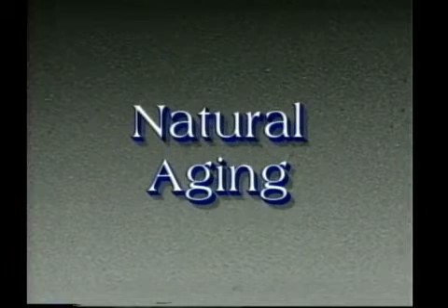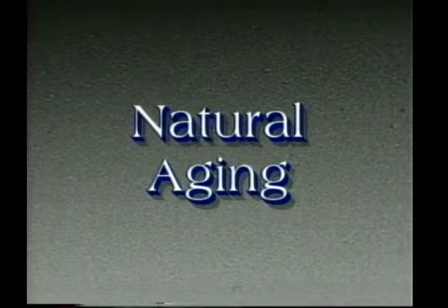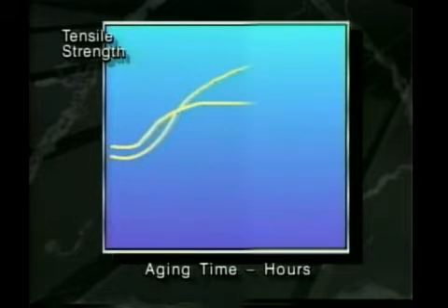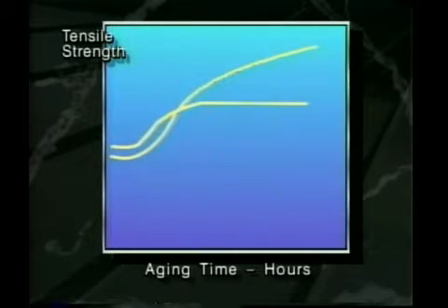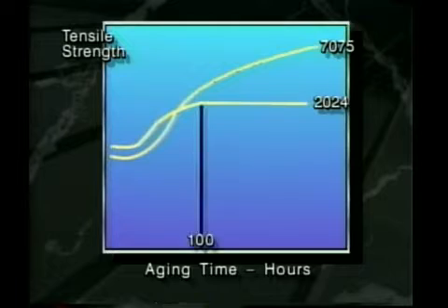When aluminum alloys are naturally aged at room temperature, a gradual increase in the tensile properties occurs as aging progresses with time. The rate of increase and the final properties achieved vary with each alloy. The illustration shows the increase in tensile and yield strength as two more common heat-treatable alloys, 7075 and 2024, are naturally aged. It can be seen that the natural aging response for a 2024 alloy is completely different than for a 7075 alloy. For both alloys, the tensile strength increases steadily with time for the first 100 hours.